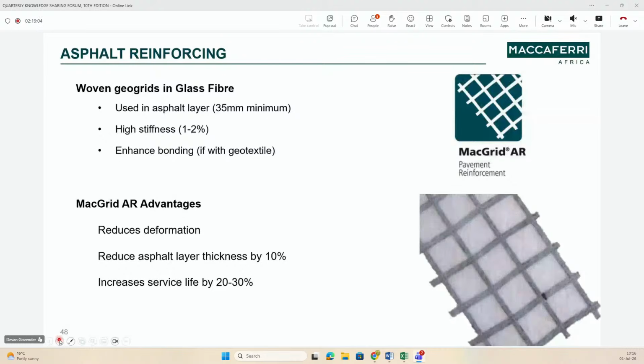Now, arguably, as I said to you, in South Africa or Africa, our pavement layers are slightly thinner, so the road mesh product is not suited unless you're going with thick asphalt overlays like this, which is not unheard of, because if we look at heavies, lots of trucks coming through, then we can consider thick asphalt overlays like that. This is the milling of the material that you can see, the crack sealing, the road mesh deployment, the road mesh fixing, and then the wearing course that's being applied, and then of course the finished surface thereafter.